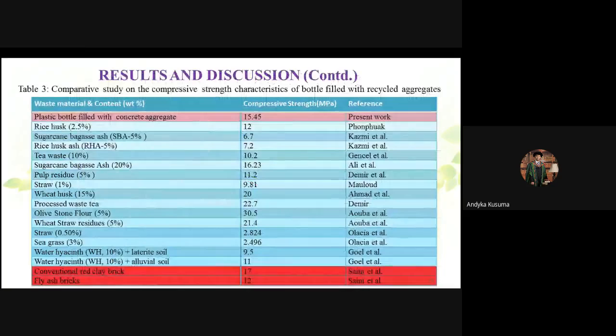This is the detailed literature review, and it's a table showing a comparison between the compressive strength of our specimen and that of conventionally used red clay brick, fly ash bricks, and bricks made from agroaquatic waste fibers. For a good building brick, the compressive strength should be greater than 3.5 megapascal, and from the experimental work, we have got a compressive strength value of 15.45 megapascal.